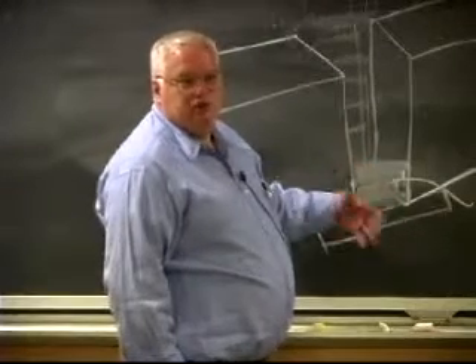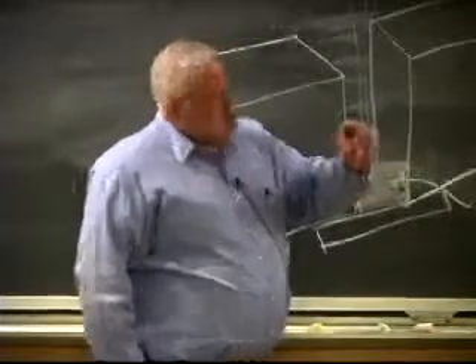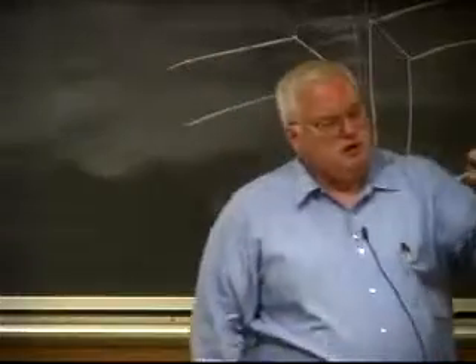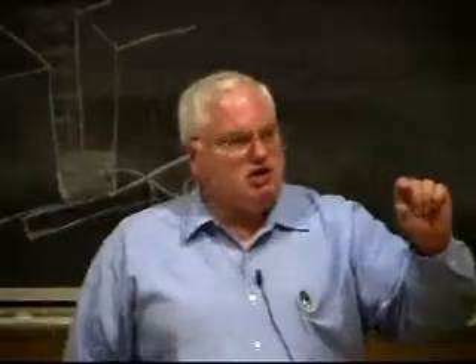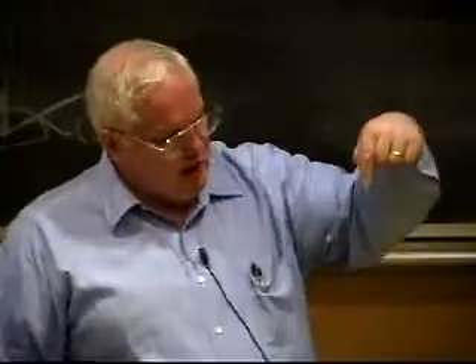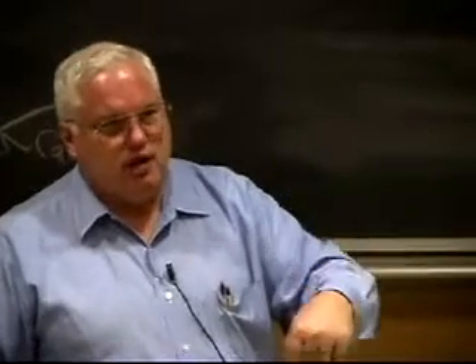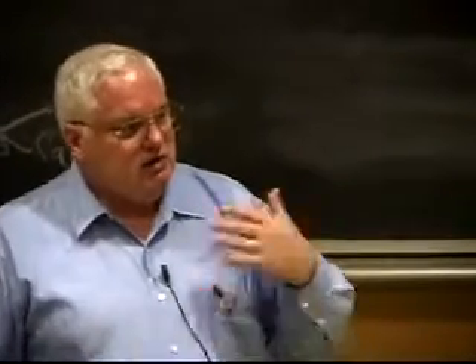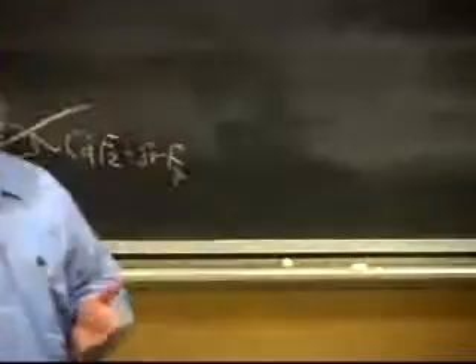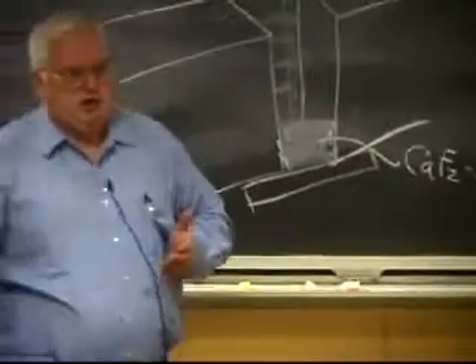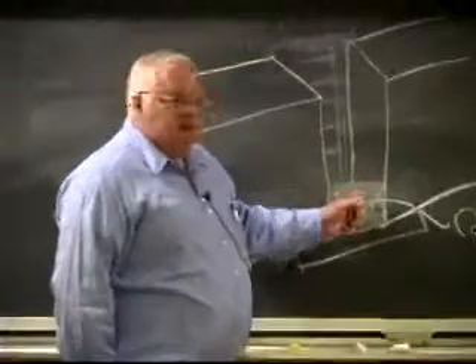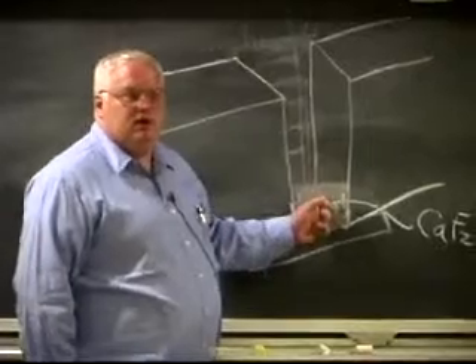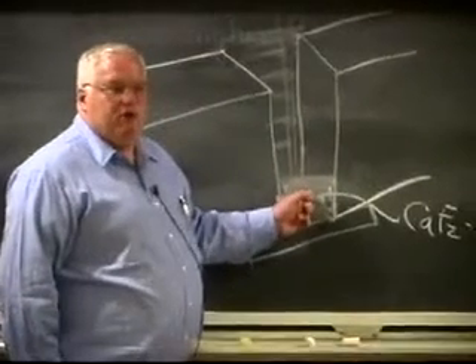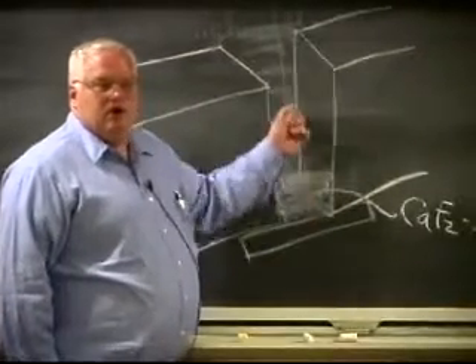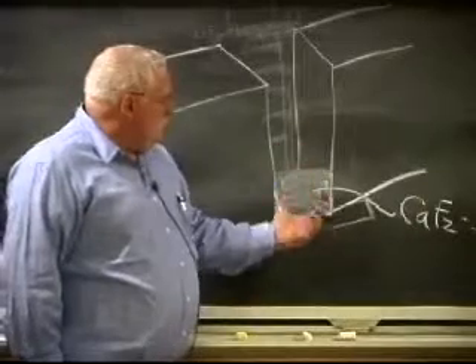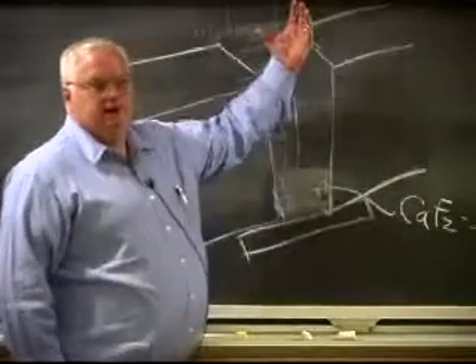The arc starts by melting everything. Once you get this layer of molten fluoride, which might be at the end an inch, inch and a half deep, you just feed the wire in there while you're passing 1,000 amps, and it resistively heats the molten fluoride, electrical resistance heating. And the wire is feeding into this 1,400, 1,500 degree centigrade molten flux. With current going through the wire, you melt off drops of wire, which just make a casting going up.